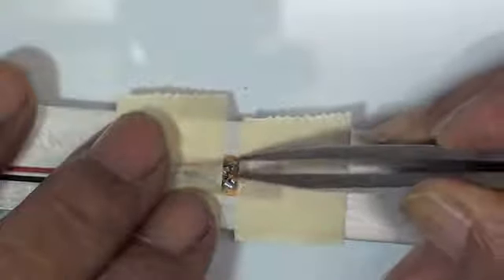We also use a sharp tweezer to position the wire right on top of the tinned parts on the solder tabs. And now that everything's held in position, you don't have to have three hands now. You've got everything taped firmly in position. It's ready to solder. You can use two hands to do the soldering now. Always have a small pool of solder on the tip, which helps the soldering process. And it's done.